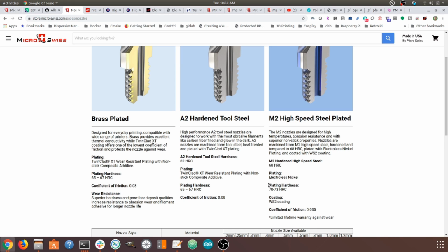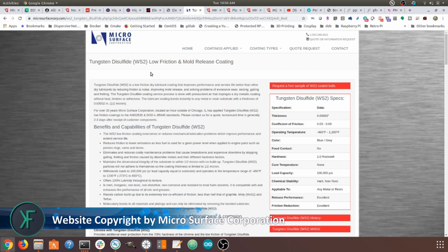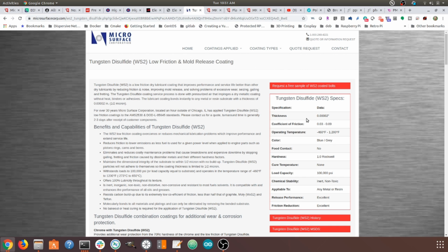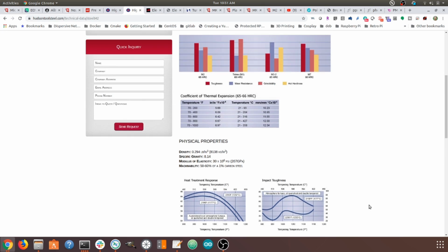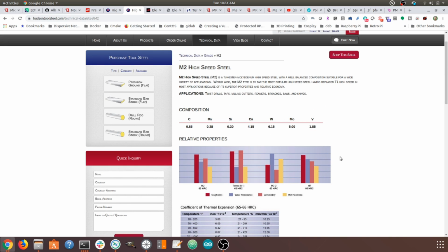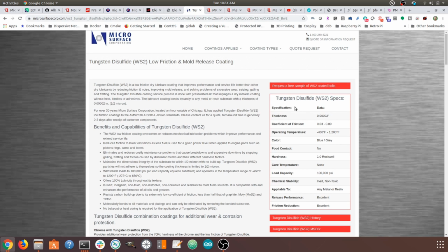And as you can see here, that plating is even harder than the plating here, so it gives us extra hardness. And then it has a WS2 coating, because that's going to take our coefficient of friction to less than half of the coefficient of friction that we found on the Twinclad XT. WS2 is exactly what it says it is, which I really kind of enjoyed seeing. WS2 means we have a tungsten disulfide. So we not only have a high tungsten content in our high-speed steel, as we showed back here, we have also added a lot of tungsten to our coating here.